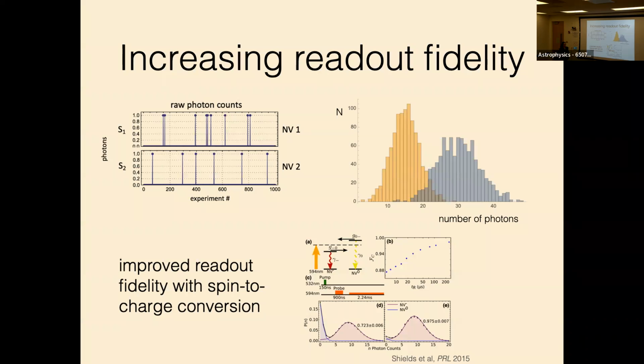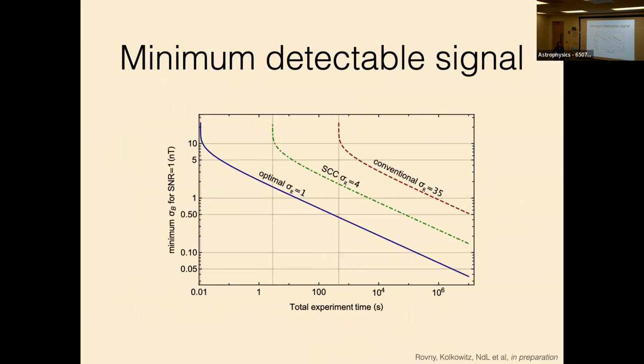At the time, we were very excited about this, and then immediately not excited about it, because you can see that this readout window here is something like 2 milliseconds. This normally doesn't help you at all, because if you're doing normal magnetometry, taking this overhead of 2 milliseconds is really catastrophic, because all that you care about is how small of a magnetic field you can measure with some integration time. If I add this 2 milliseconds of overhead per shot, then you're never increasing your sensitivity. So it's not useful for traditional magnetometry, but extremely useful for this covariance sensing.